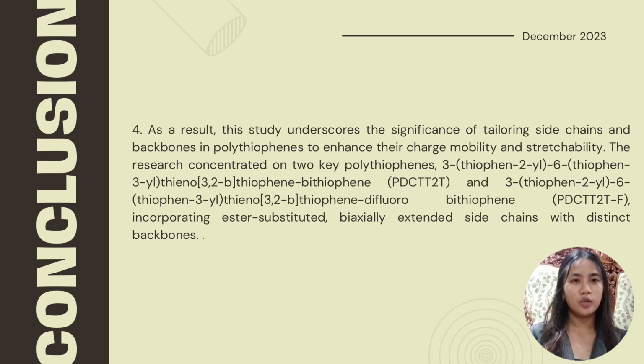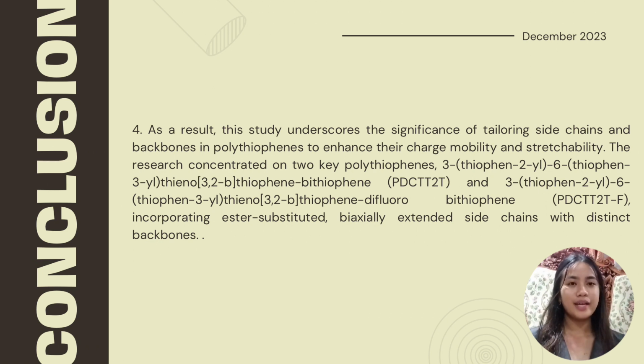The research concentrated on two key polythiophenes, PDCTT2T and PDCTT2T-F, incorporating ester substituted biaxially extended side chains with distinct backbones. It reveals a synergistic effect between backbone fluorination and ester substituted side chains, resulting in improved mobility-stretchability properties, particularly in highly stretched states. The biaxially extended side chains enhance intramolecular charge transfer and induce a more amorphous structure, while backbone fluorination steepens the structure, enhancing intrachain charge transfer.